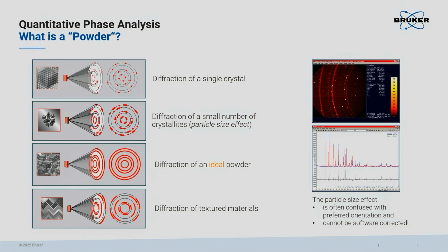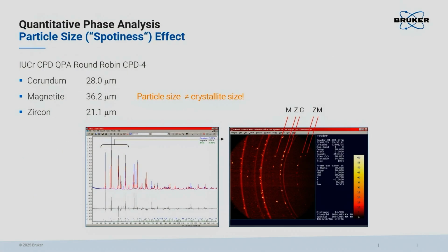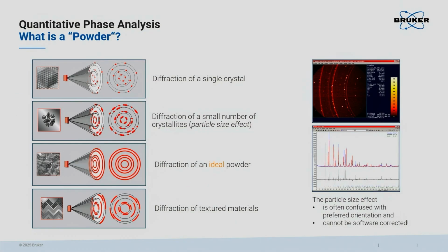So one of my favorites is the so-called spottiness effect. It has also been discussed yesterday. If you are deviating from an ideal powder, you have issues like diffraction of only a too small number of crystallites, which will give you a 2D intensity distribution like this one here. Or you have preferred orientation maybe, which gives an intensity distribution shown here. In any case, requiring corrections. The problem with this small number of particles, however, is it's entirely random. There is no correction available for that. If you encounter this problem, you are essentially done with your analysis. You either have to re-prepare your sample or you have to find a better sample. This is one of the most important limitations, and you wouldn't believe how often we see such powders and such data in the application lab in my company. It is one of the most frequent problems we can see in user data.